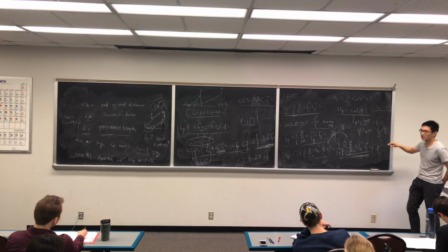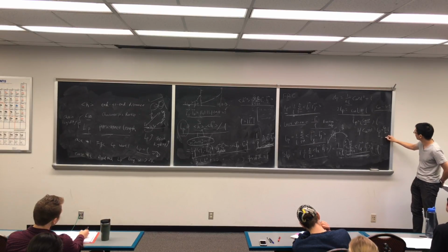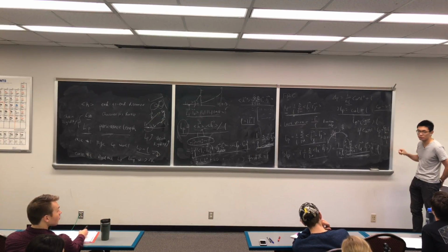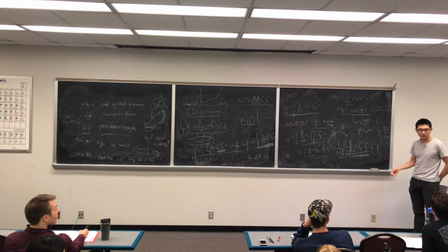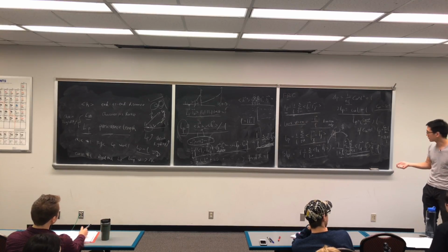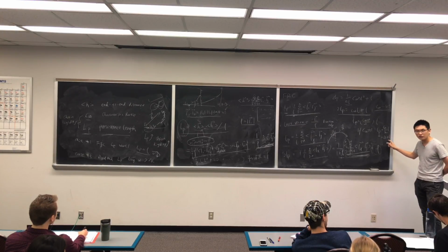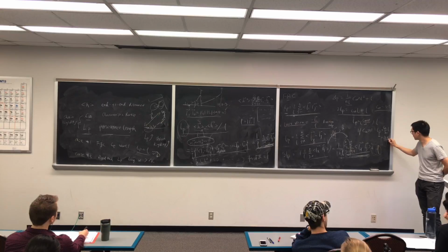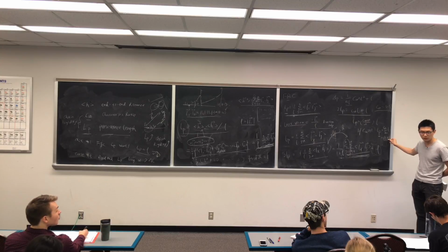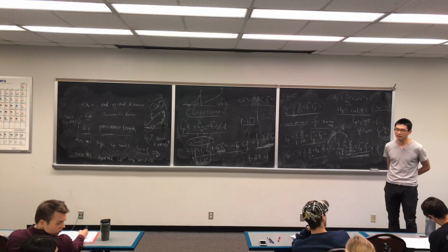So the persistence length would be about 1.2 up to 2.2 times the bond length, for a typical FRC free rotation model or hindered rotation model. So this would be this value, okay? This is the individual bond. The physical meaning is that after roughly 1.5 bonds to an average of 4 bonds, your chain is bending 90 degrees. So it's a relatively flexible chain.